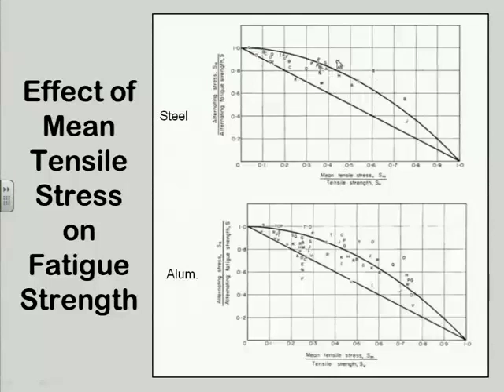The lines that you see drawn on them have names. The parabola is called the Gerber parabola, like the baby food. And the straight line is called the Goodman line, and both of those are researchers who came up with the concept to look at the data in that respect. You can see that the Gerber line pretty well goes through the middle of the scatter and is considered to be a good fit to the data, even though the R squared value is not going to be very large because you've got a lot of scatter in the data.